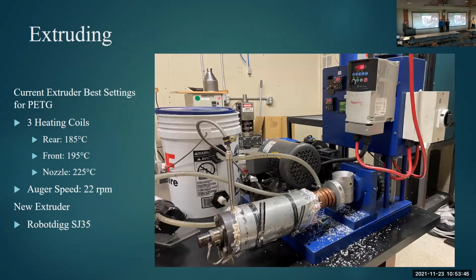All right, so then we come to the extruding, of how do we actually get our materials so we can 3D print it. This is the extruder we're currently working with. Material goes in the hopper to the auger screw. We actually have a cooling coil here to prevent heat from coming back to where the pellets are, because we don't want them to melt before reaching the auger and get stuck.